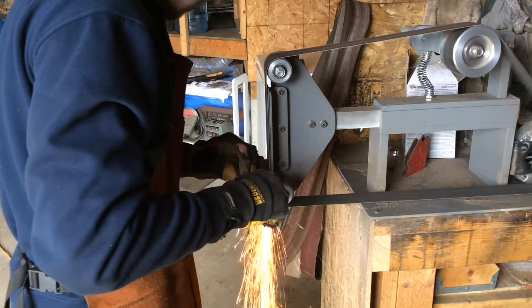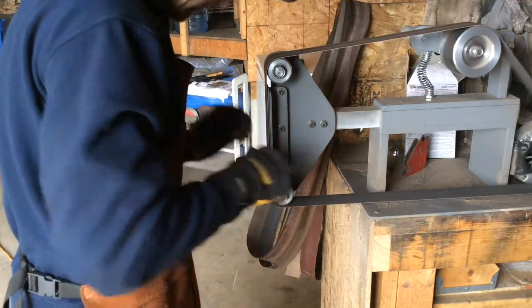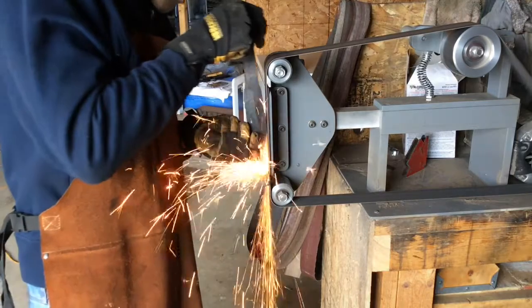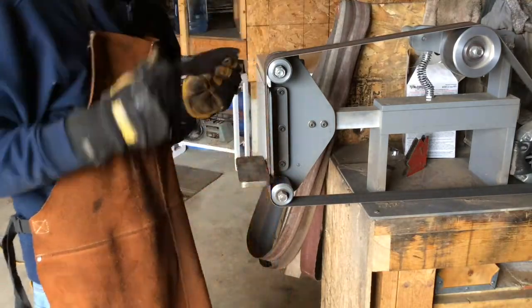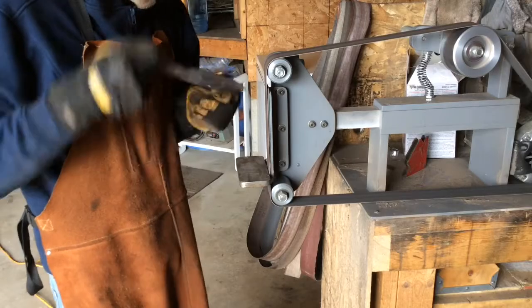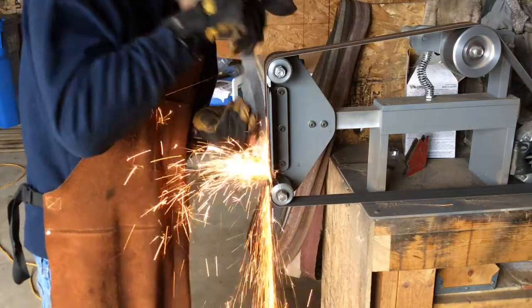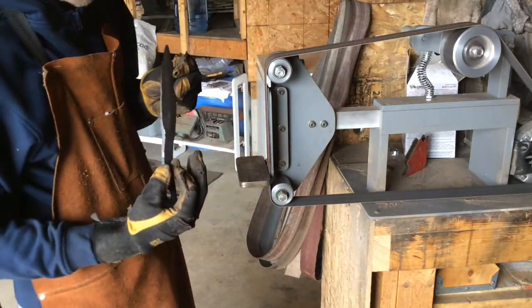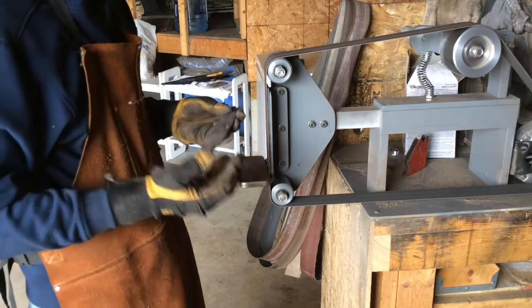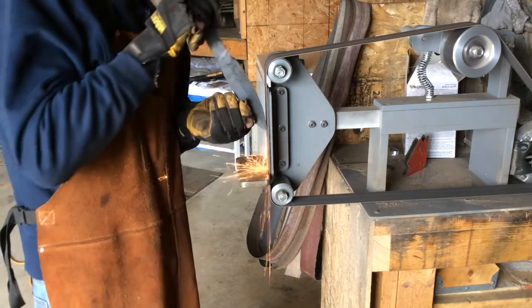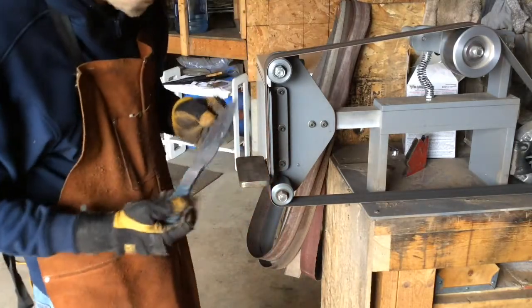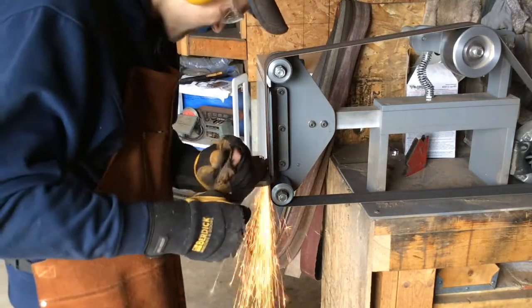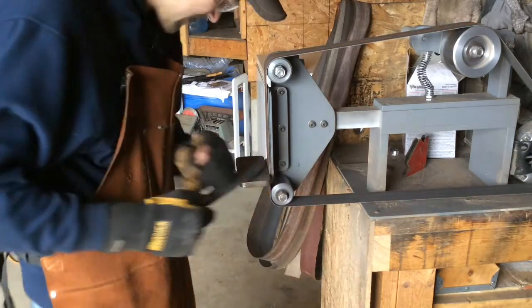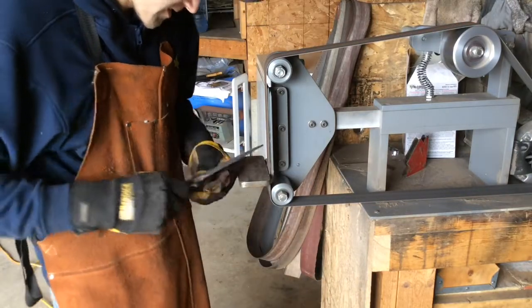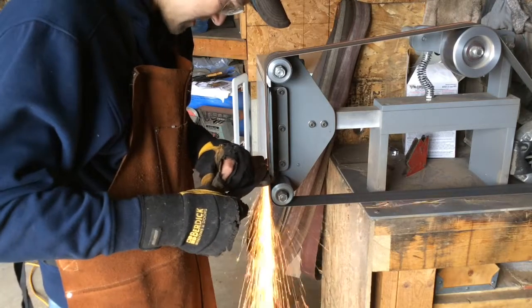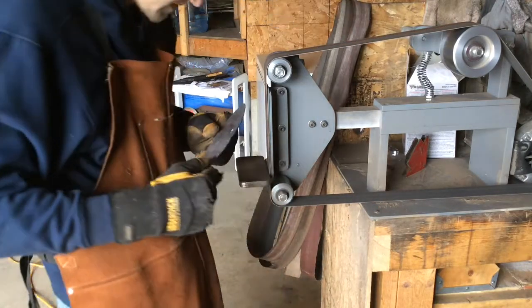Now that the blade is annealed, I'll begin the grinding. I'll start by truing up the shape of the blade, keeping in mind that I need the point to be perfectly in line with the hole in the back, so that everything is balanced correctly. I'm going to take my time and just go slowly so that I have everything all lined up. I'm using a 36 grit aluminum oxide belt running at 1750 RPM, which removes the material incredibly fast.